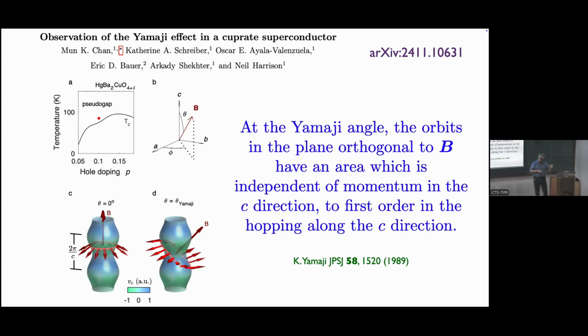One special thing about the mercury compound is a very simple structure. It's purely tetragonal with the layers right on top of each other. In this case, you just have a simple cosine dispersion along the C direction, and a very small modulation, which is greatly exaggerated here. Then there's something called the Yamaji effect, which is the following. The electrons semi-classically will move on this orbit, which is orthogonal to the field.